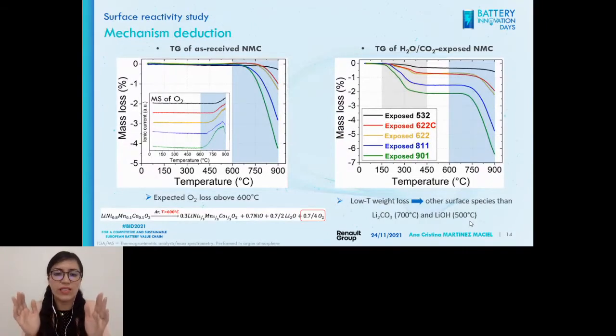You can see there is a huge weight loss from 600 degrees, which is normal—it's related to the production of oxygen, as you can see in the reaction at the bottom. So it's the regular thermal decomposition of NMC materials. The as-received samples were just used as a reference, what we have at the beginning.